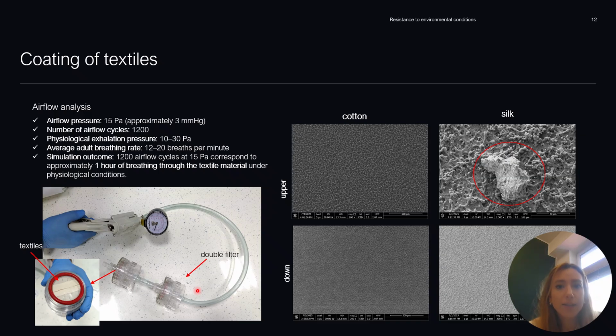Similar to the peel adhesion test, the airflow experiment demonstrated excellent retention of the nanocomposite within the textile structure. In the case of silk, only a single graphene sheet was detected on the surface of the upper filter, because here we used a double filter. The use of a double filter system allowed us to assess the potential release and transport of nanocomposite fragments through the airflow pathway. The absence of graphene oxide sheets on the lower filter for both textile materials indicates that the nanocomposite may remain strongly associated with the fabrics.